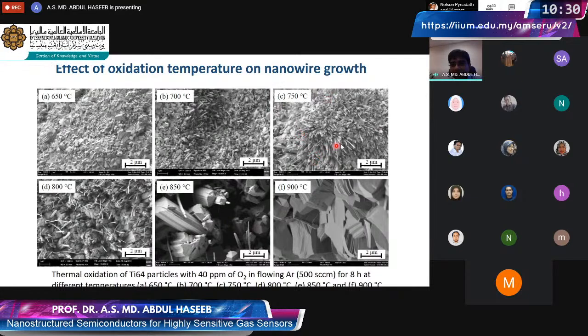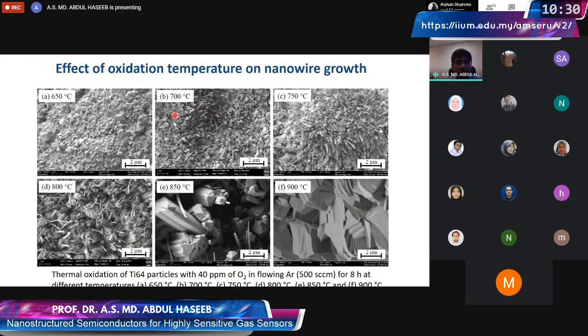For instance, we see a few of them here at 750, a few at 800, and so on. Quite very few at 700 also. So our temperature window, as we determine here, will be about 700 to 800. And we will show later on that probably 750 is the best temperature that we could use.